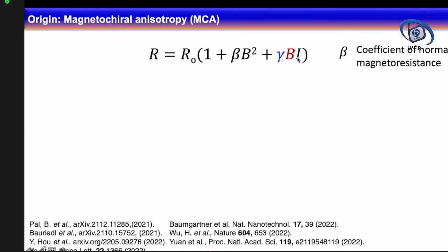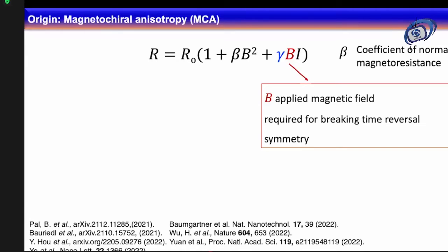B is the magnetic field, I is the current, and gamma is a coefficient that remains constant. But here, with magnetic field and current, if you change the sign of B or you change the sign of the current, then you will have a change in the sign of this last third term, which would give you the anisotropic behavior, meaning the resistance would change, and that we call the chiral magnetoresistance. When you apply the magnetic field, it means that you are inducing some kind of magnetism in your material. And that means that time reversal symmetry is broken, meaning that your order parameter is now antisymmetric as a function of time.